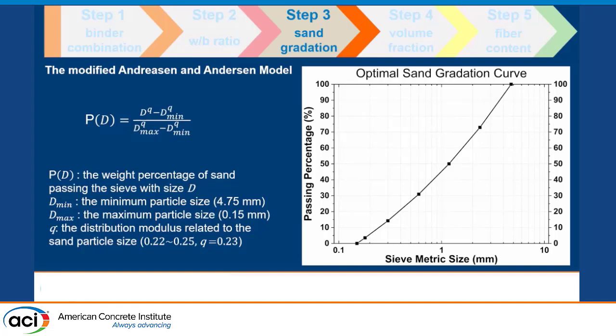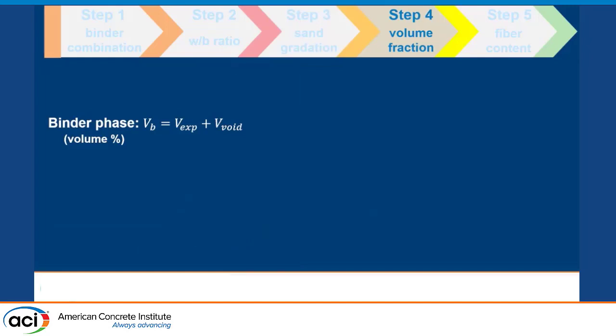Okay, so for the optimized sand gradation, we will employ the modified Andreasen model to achieve the optimal sand gradation curve. We did the sieve analysis of most of the sands available on the market, but they look much finer than this curve. So we find that it is pretty difficult to simply blend sands from different sources to achieve our desired sand. So finally, we decided to sieve the sand first and then blend the sand with the exact percentage at each gradation to have the sand with the desired gradation curve.